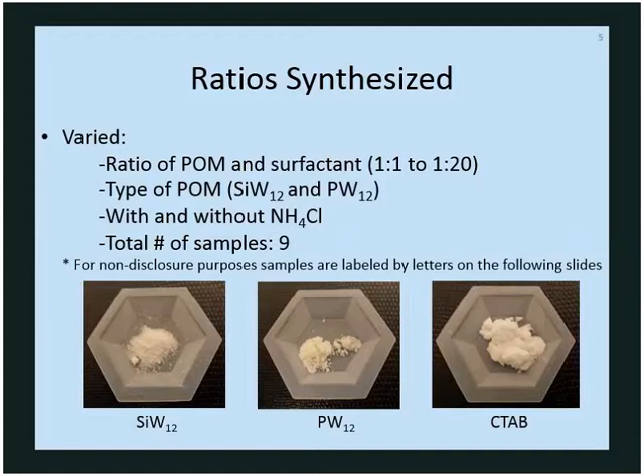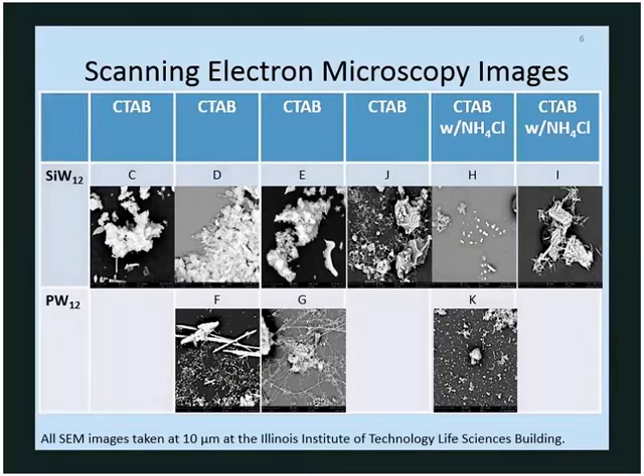For non-disclosure purposes, the following slides will have numbers instead of actual letters. As you can see here, the scanning electron microscopy images were all taken at 10 microns. The first row is silicotungstic acid, which exhibits more of a sheet-like structure, with layered sheets piled on top of each other. And then in adding the ammonium chloride salt, it caused it to ball up, which was not as desired. And then changing the inorganic core to phosphotungstic acid caused long, rectangular structures to form, which became very long and broke off. So that was not as desired either.